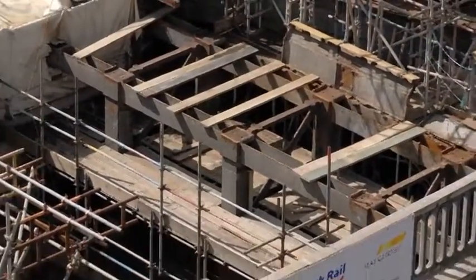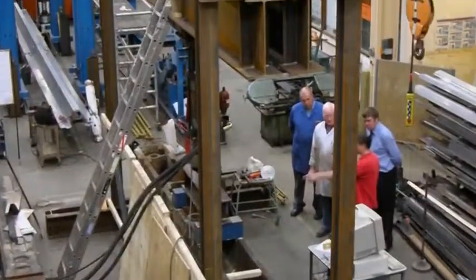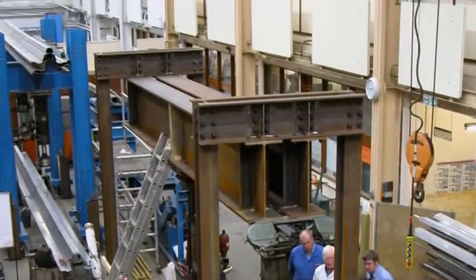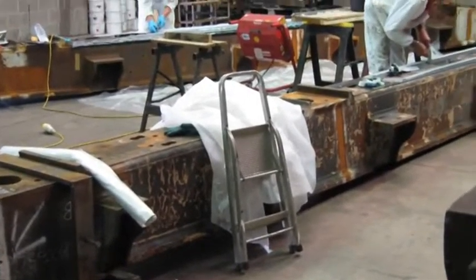To confirm their suspicions, they removed some of the beams from a less-used part of the bridge and sent them to the metallurgical lab at the University of Manchester, where they were tested to destruction. From this they could calculate the strength of all the other beams, and then, in the interests of conservation, they rebuilt the test beams and put them back where they wouldn't have to carry any serious weight. Meanwhile, they set about working out just how much stress the bridge had suffered over the years, by calculating every train, passenger, and freight movement since 1849 — a massive job, which they did with the help of the National Archives at Kew.